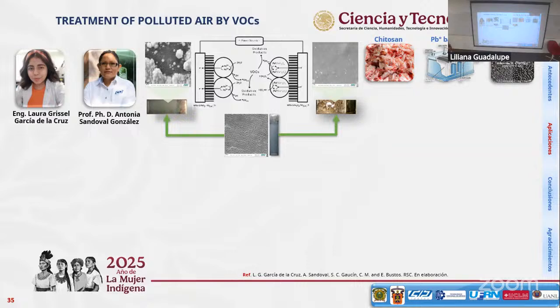Chitosan we obtain from shrimp waste, and it's important because when we use this kind of waste, we promote a better distribution of the iron and a higher concentration of hydroxyl radicals for the removal of volatile organic compounds. Additionally, we want to valorize lead from batteries, because these batteries are observed in different places but without any other action about them.